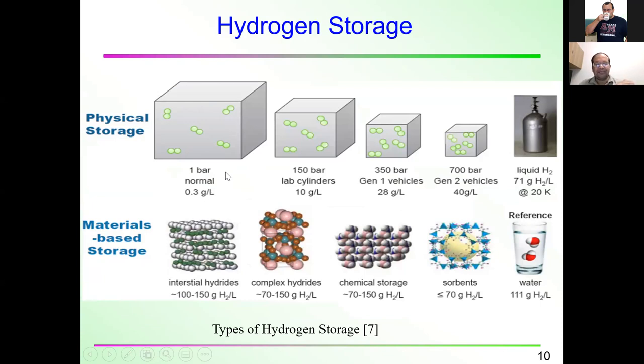If I increase the pressure to 150 bar, I can store only 10 gram of hydrogen per liter volume. Further increasing the compression, at 350 bar pressure, I can store only 28 gram. If I increase more, to about 700 times atmospheric pressure, then I can store as much as 40 gram of hydrogen per liter. But liquid hydrogen is 71 gram.